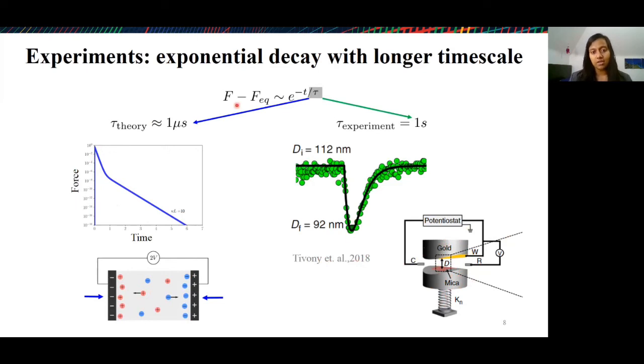So the good thing is that the evolution of force that is experimentally observed does follow an exponential decay. However, there are still some big gaps between our theory and the experiments. The main issue is that the timescales observed in experiments are much larger than that obtained by our theory. In our theory, for the given experimental conditions, the timescale predicted is about a few microseconds, but the actual experimental timescale is on the order of seconds, and so this is quite a big discrepancy.